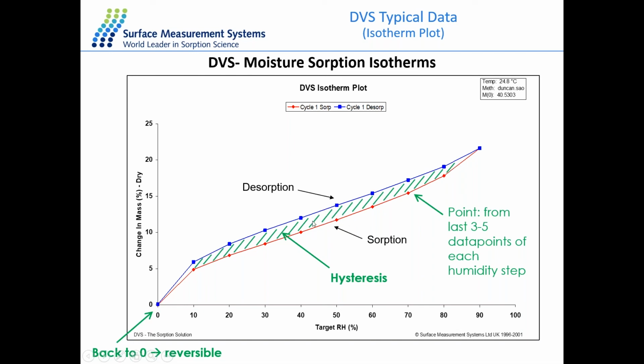And there is a gap in the middle, which is the hysteresis gap, just confirming that during the desorption, the water molecule is not only on the surface, but going to the bulk. But during the desorption step, it's a diffusion limited process that gives different kinetics compared to sorption. And if the shape of the isotherm is very close to a type 2 or type 4 isotherm, we can also use the BET theory and the BET equation to calculate the surface area of the material from the desorption isotherm as well.